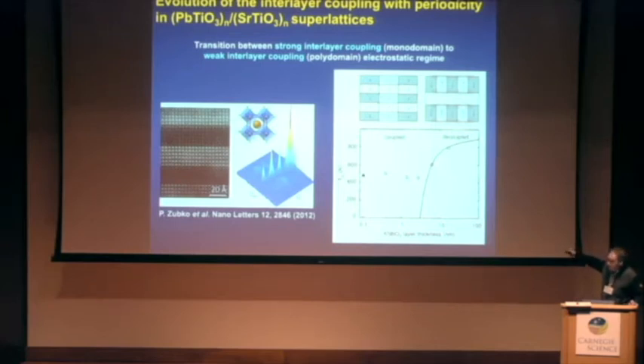if we have a thin enough periodicity in the lead titanate, strontium titanate superlattices, the system may adopt a uniform polarization structure where the out-of-plane component of the polarization is constant throughout the structure. So in this particular case, the ferroelectric layers are electrostatically coupled, and the price to pay for this is that we have to polarize the dielectric layer and somehow reduce a little bit the polarization in the lead titanate.